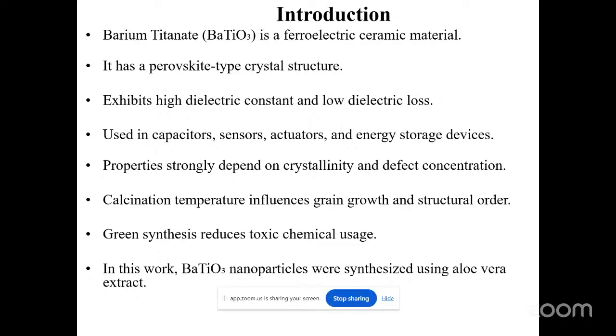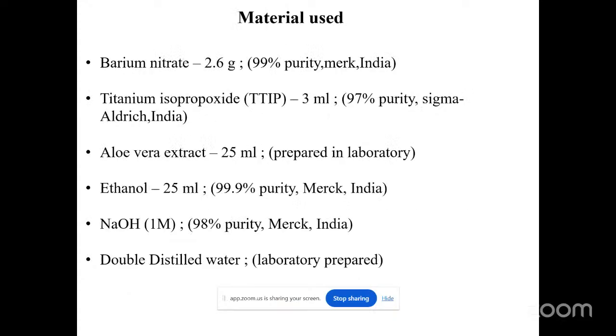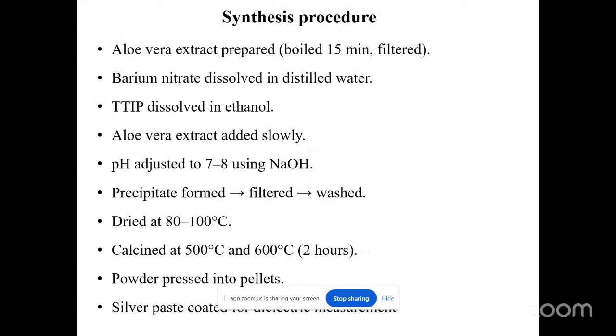In this work, we synthesized barium titanate nanoparticles using aloe vera extract through a green synthesis method, which reduces the use of toxic chemicals. The main precursors used were barium nitrate and titanium isopropoxide. Aloe vera extract was used as a natural reducing and stabilizing agent. Ethanol, NaOH, and distilled water were used during the synthesis process.